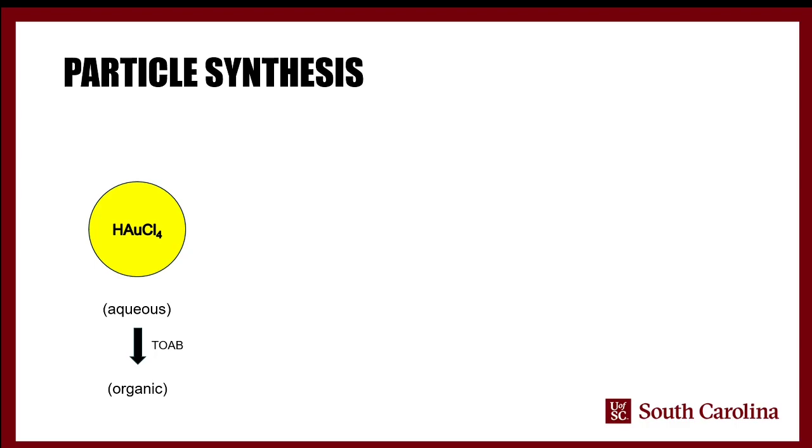And the ligands matter, because the bulkier the ligand is, the more difficult it is to actually observe a collision. If the ligand is too bulky, the particle never gets close enough to actually carry out a reaction and be in electrical contact with the electrode. I'll talk a little bit more about that coming up. So you kind of have to choose very carefully.